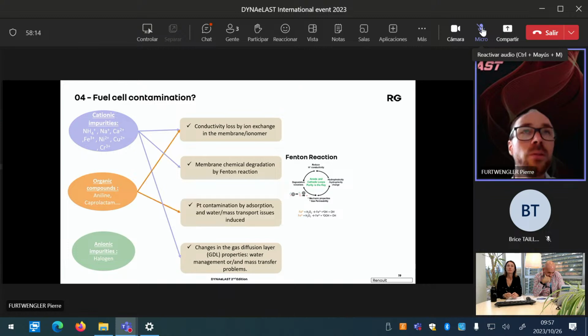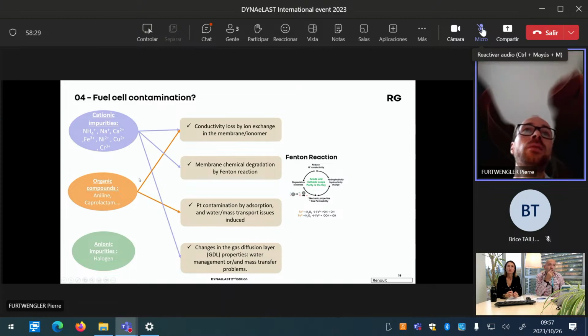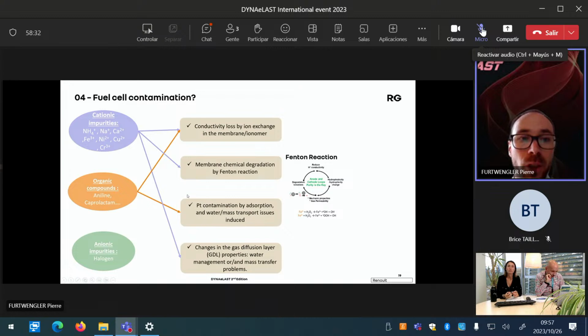All the organic compounds are mainly from the monomers. So here I have examples with aniline or caprolactam. Caprolactam is more from the polyamide world, so maybe a TPA. It's not so common, but whatever you have as monomers going inside, we have the same kind of problem. You can have platinum contamination. As the platinum is involved in many chemical reactions, it will be occupied to do something else than working for the fuel cell. And we will also have a loss of the kinetics and the efficiency of the fuel cell because of the membrane, which will be impacted by this compound.